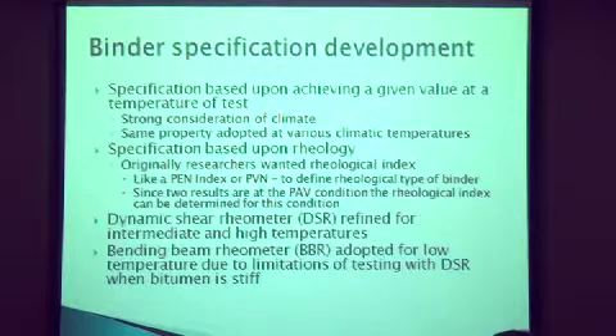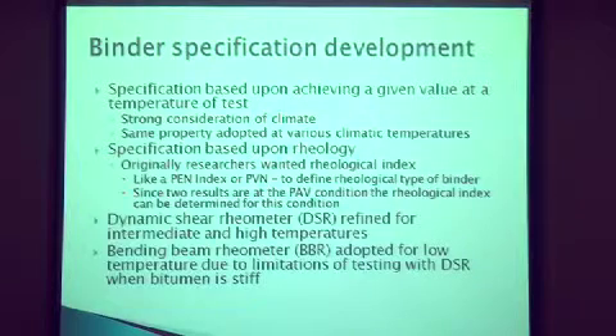So what we did is we specified the bending beam rheometer stiffness, and we specified the stiffness with an 8 millimeter dynamic shear rheometer on the PAV binder, and it was a back way of introducing the rheological index to the specification without calling it the rheological index. So it was an easier way of getting it in.